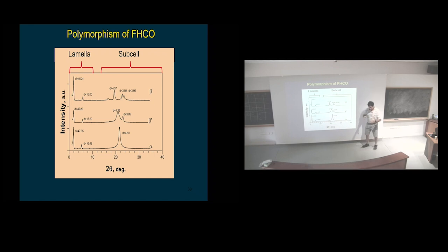But look at this cool thing. Remember how the alpha is metastable and trying its best to crystallize, but it's a catastrophe? Look how much bigger it is, 47.3. It's hexagonal, so it's standing like this, the chains, and they're big. And then when it goes to beta prime, it goes, oopa, and it tilts a little bit and becomes like 45. And then it goes a little more, or whatever it decides to do, does whatever it wants. And it goes to the beta form, so you see it goes from 47 to 45, maybe, and then it stops. It seems like that was enough to get to the most stable form.